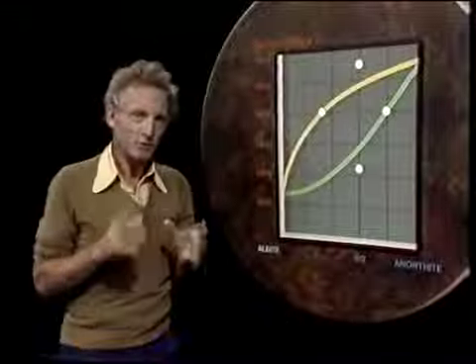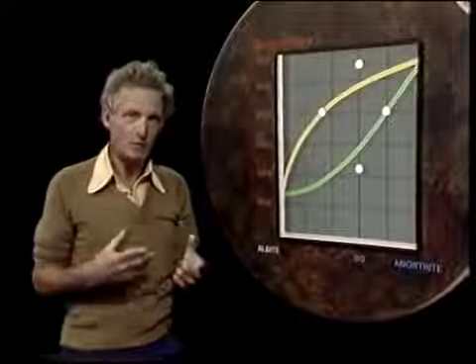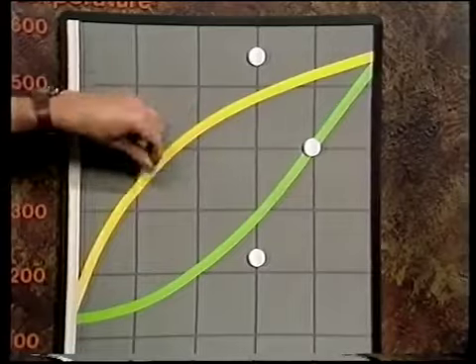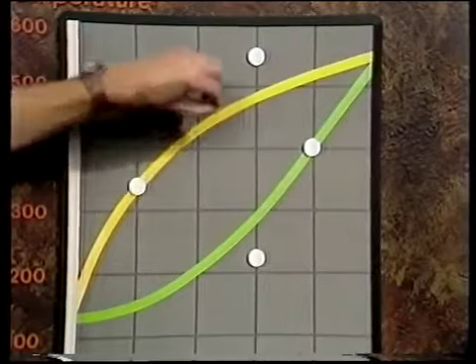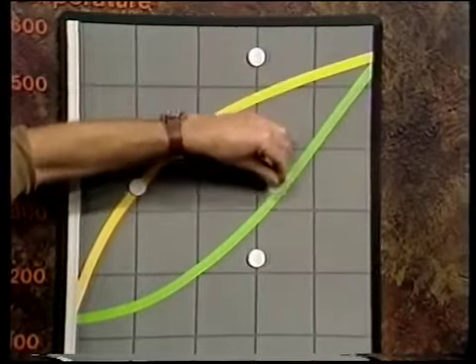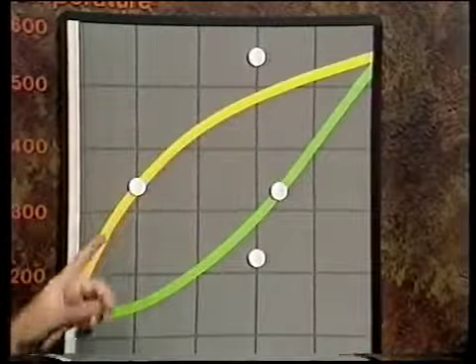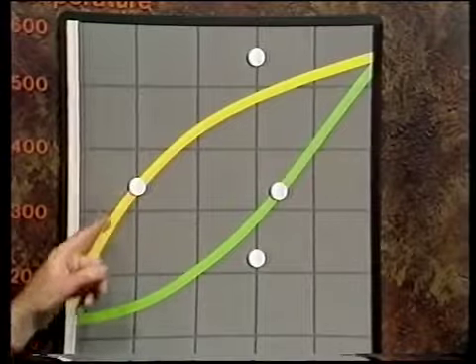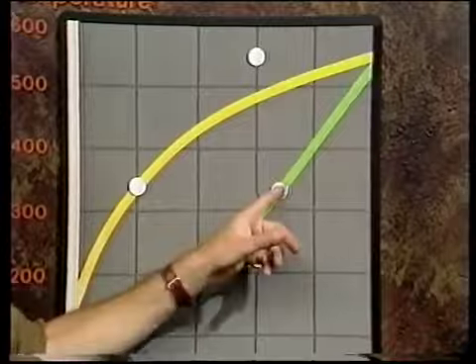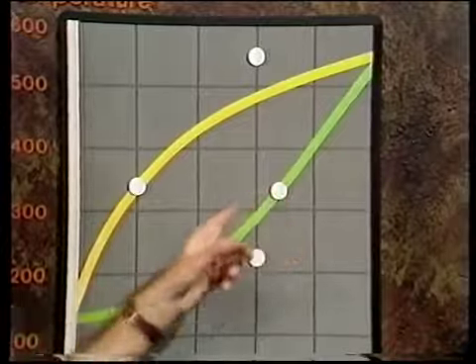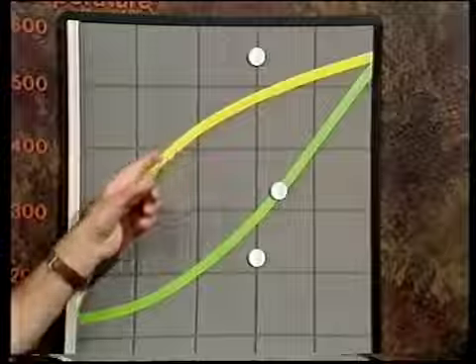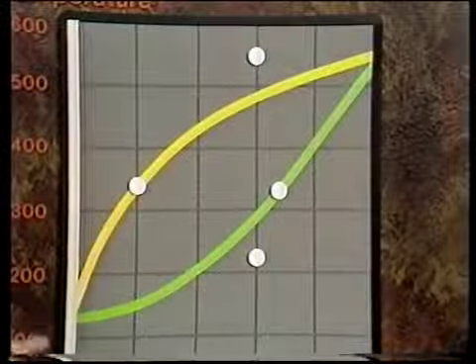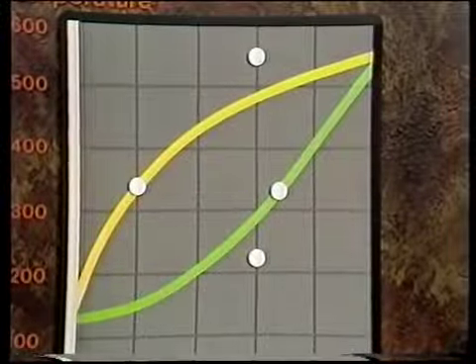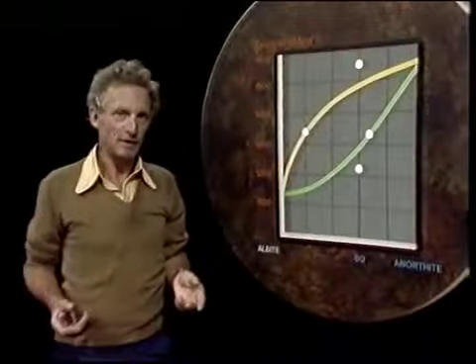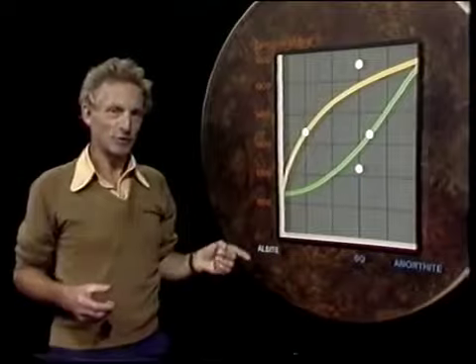There's got to be continuous reaction, continuous diffusion of ions between crystal and liquid, so that as the liquid cools and changes composition along here, the composition of the solid changes along here. And at any particular temperature, the liquid is always richer in albite than are the crystals. And as cooling proceeds, of course, both liquid and solid get richer in the albite component. But that's got to stop somewhere. And it's fairly clear where it's got to stop.